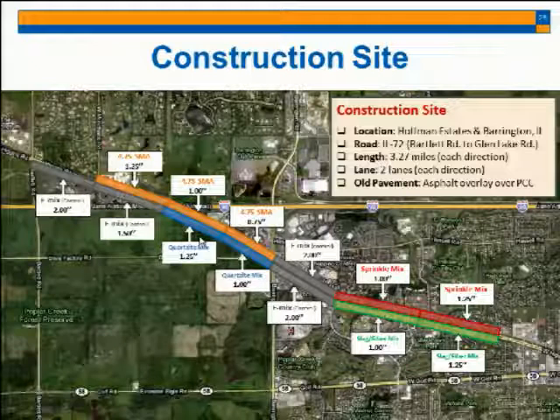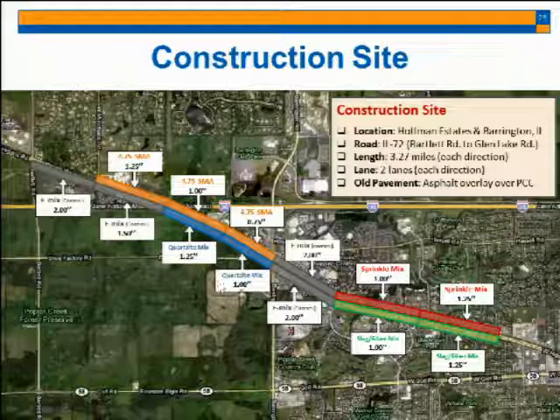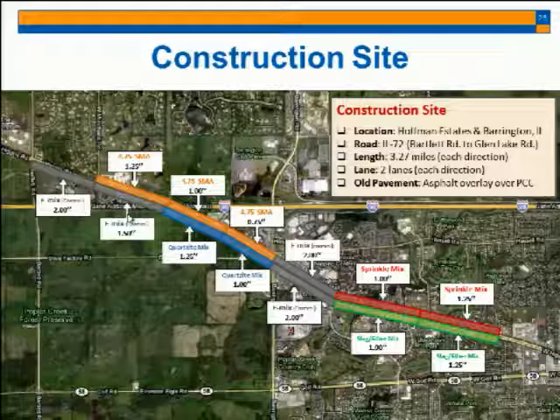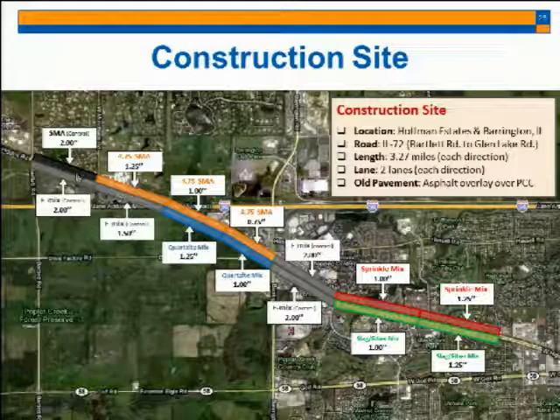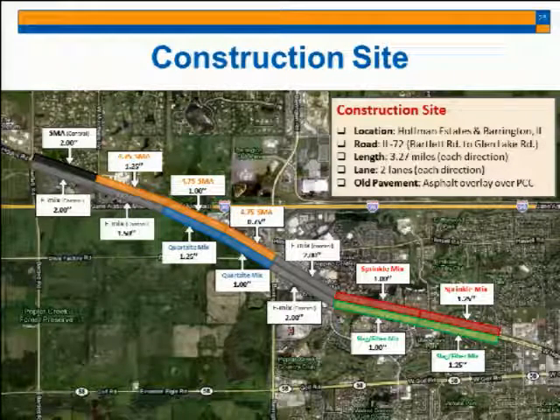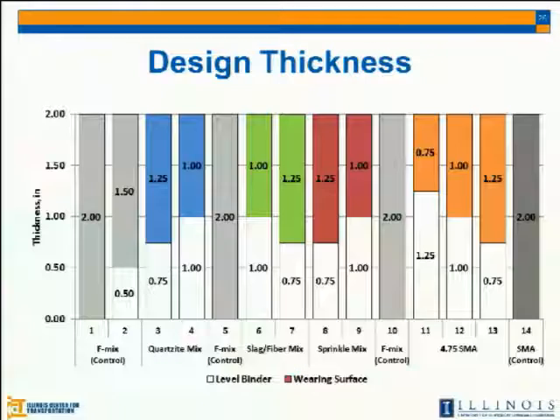For our new mixture, we placed these materials at 2 different thicknesses. One is 1 inch, another one is 1¼ inch. But we tried to place the F mix at 1¼ inch too, but it didn't work, as I mentioned, because of the compactability issue. So the 4.75, 12.5 control mix cannot make even 1½ inch of thickness. So 2 inch was the minimum thickness they can make. So we had the 2 inch thickness of the surface layer.